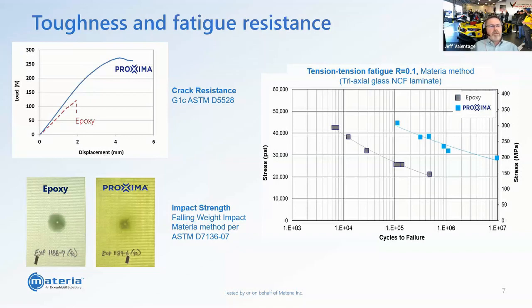So if you have automotive applications where you're looking at reducing the damage from an impact area, again, with this falling dart impact, we can show here we typically have a significantly smaller impact area with our materials versus the epoxy sample that we're using. And then looking at tension fatigue, you can look at other different fatigue testing, but we're able to significantly increase the cycle times to failure with our material versus a standard composite setup.